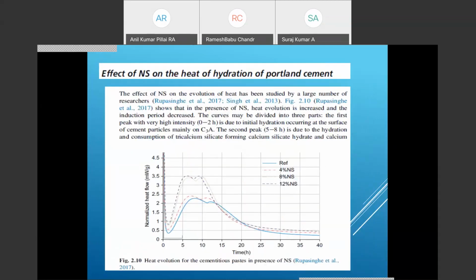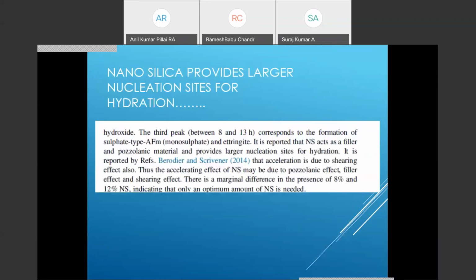Effect of nanosilica on the heat of hydration of Portland cement. The effect of nanosilica on evolution of heat has been studied by a large number of researchers. Here is a curve which represents the heat of hydration versus time. First of all, you can see that the heat of hydration is divided into 3 parts. The first peak with intensity 0 to 2 is due to initial hydration occurring at the surface of cement particles, mainly on tricalcium aluminate. The second peak is due to the hydration and consumption of tricalcium silicate, forming calcium silicate hydrate and calcium hydroxide. The third peak corresponds to the formation of calcium sulfate type, monosulfate and ettringite. It is reported that nanosilica provides larger nucleation sites for hydration.